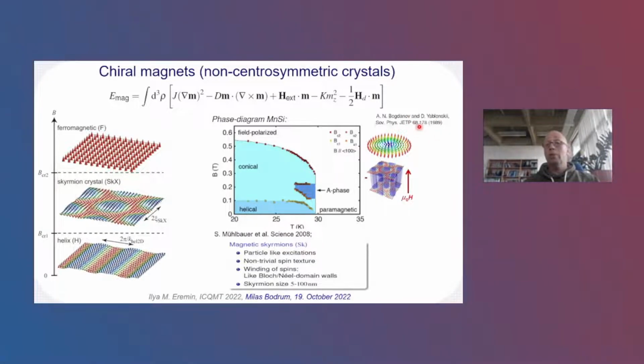The first who looked at it were Belavin and Polyakov, in the context of the nonlinear sigma model, before Bogdanov and Yablonskii in a ferromagnet. But the proposal to realize magnetic skyrmions in the form of skyrmionic lattices came from Bogdanov and Yablonskii back in 1989, where they were playing around with the total magnetization energy of a ferromagnet, with a strong Dzyaloshinskii-Moriya interaction, which means a strong spin-orbit coupling. And they found that if you put the system in an external magnetic field, of course, you can also have other terms like crystalline anisotropy and so on.